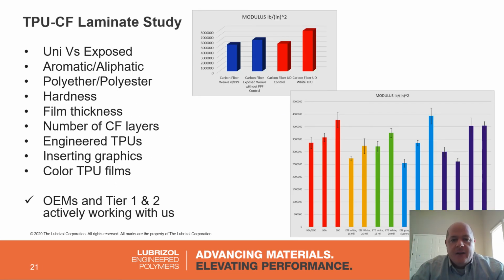Again, we're talking about different stack ups of different carbon fiber with modulus. You can see, for example, the yellow bars, as in this particular case, it was an ETE grade, might be a little bit difficult to see on your screen. You can see that the modulus had increased. And then you can also see it with different levels of different kinds of TPU on the carbon fibers. But again, if this is something that is of an interest, it would take a little bit of trial and error to get your carbon fiber stack up or your customer's carbon fiber stack up used with the correct TPU to get that modulus increase.